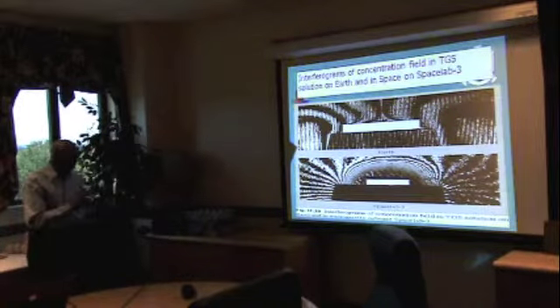I don't have a picture here for the particles, but if I take a similar picture where the particles were floating in the crystal, you could see the particles. And this is the first time we calculated that the G values in the space shuttle at that time were on the order of 10^-6 G.